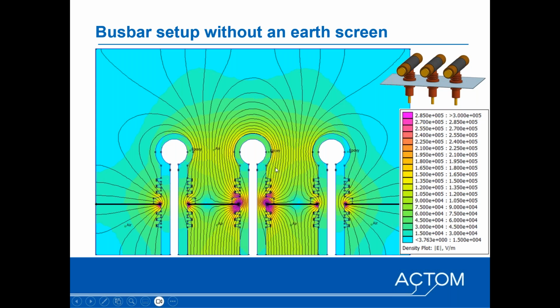So with a potential difference, and pollution on the surface of the insulation, you will then have leakage current flowing over the insulation surface. You've also got high field concentration at the interface where the bushing goes through the metal sheet, which, if you don't have a proper insulation material, or the bushing is not properly dimensioned in terms of the dielectric strength, would then cause a breakdown in that zone.